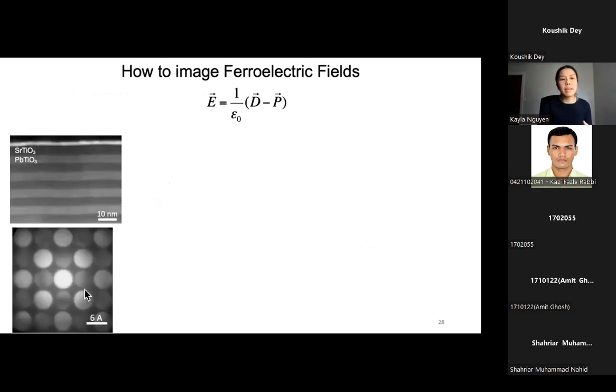So now what we can see is that we can image ferroelectric fields if we have a macroscopic probe. We're not going to look at individual atoms. Instead, our images are going to be showing intensity related to only something on the resolution of 5 to 7 angstroms. So we won't see atoms in our images, but that's fine. Another thing about ferroelectric fields is that there's a relation between the local displacement field or electric field and the polarization field. And this is something we can actually extract individually in our diffraction pattern.